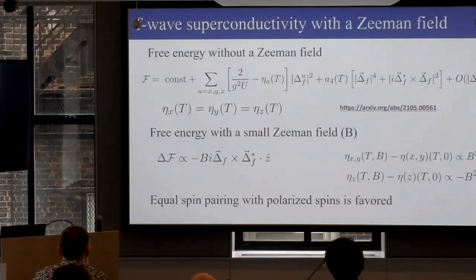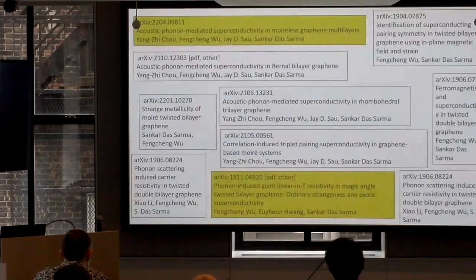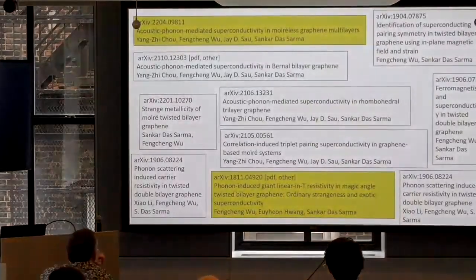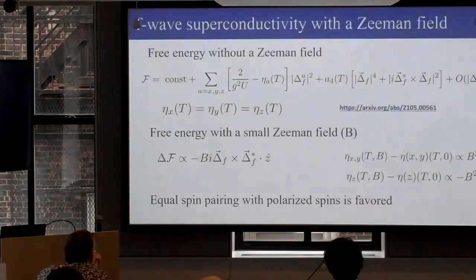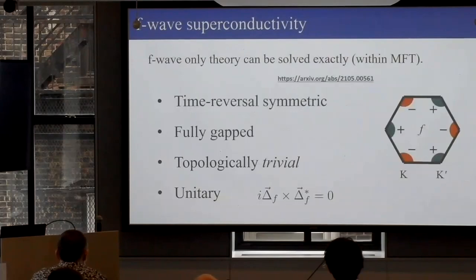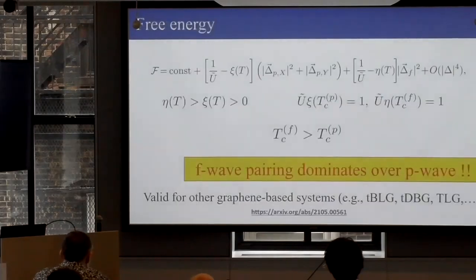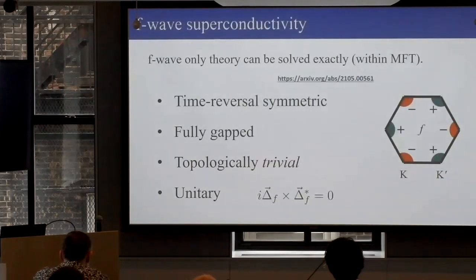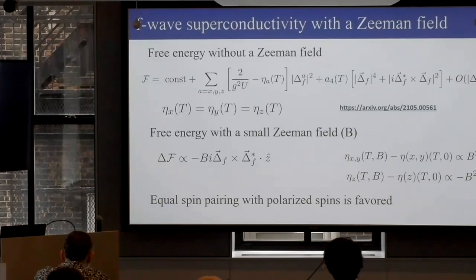Okay, and we did that. We can calculate the free energy and find out how that will change in a magnetic field. So we made a lot of predictions, and to my total amazement, this is not an important paper, but it got accepted in PRL. I think the important conclusion is that even for this you get F wave pairing, and once you say F wave pairing, we can solve the problem exactly, and then give some idea about what would happen in the presence of a small Zeeman field, and what the issue is.